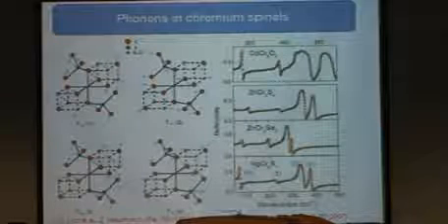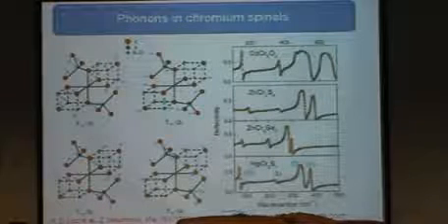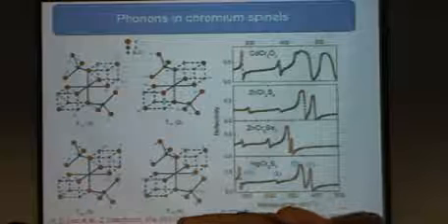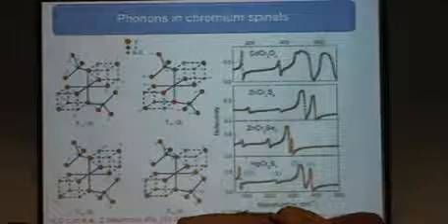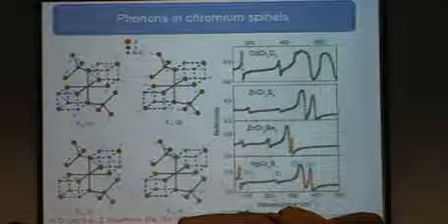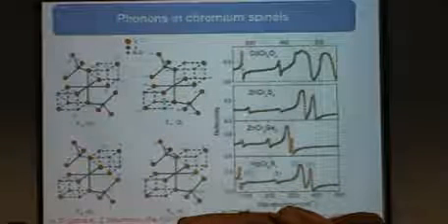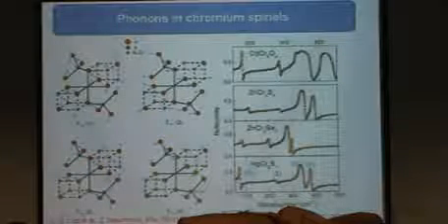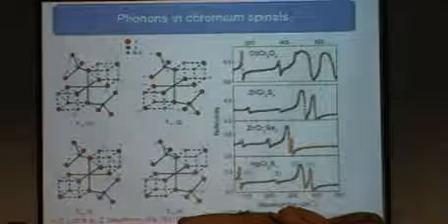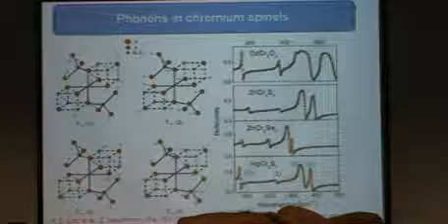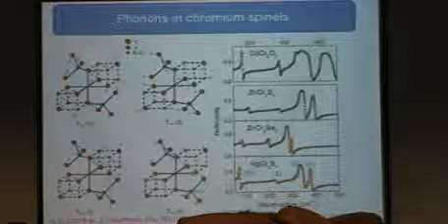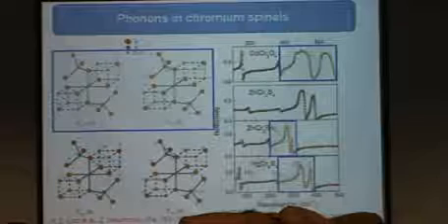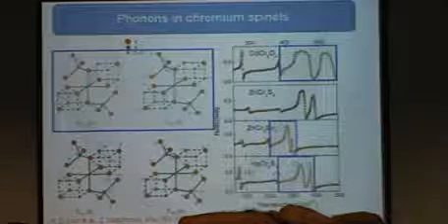For example, for this high frequency mode, the contribution of the A atom is less compared to the B site cation, while for low frequency phonon modes, the contribution of the B site is less and the A site is more. The arrows' length shows the level of contribution. But in the high pressure data, you see only these two high frequency phonon modes because of experimental limitations.